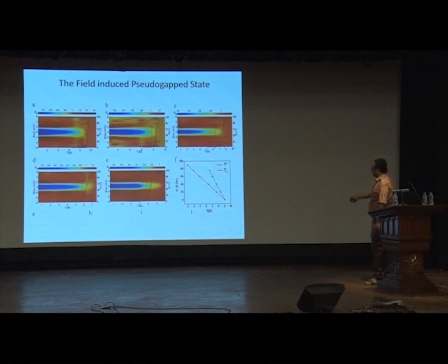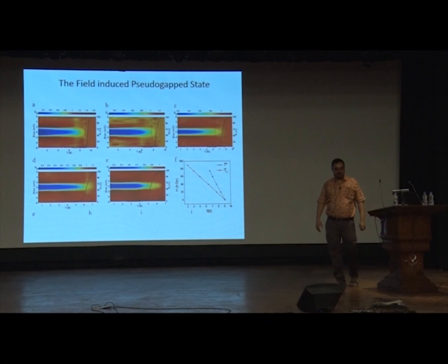In zero field, I have no pseudogap. It looks like a conventional BCS superconductor. As I apply magnetic field, this appears. So the upshot of this is that this is not just applicable for this particular system. This is not a very strongly disordered superconductor either. Many of the superconductors that we study in the lab, polycrystalline samples for example, could be very much in this disorder range.